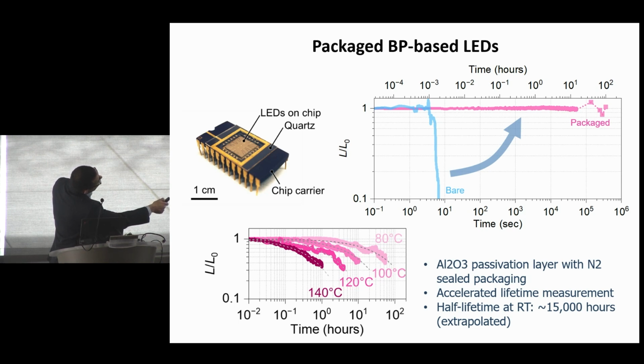Here, it looks like it's noise, but our photodetector ran out of liquid nitrogen. You're talking about tens of hours, so we had to constantly fill the liquid nitrogen in the detector. So the devices are very stable. We did the half-lifetime measurements by doing accelerated lifetime studies. That's what is being shown here. We operated devices at different temperatures, up to 140. We extracted activation energy. So the half-lifetime that we got at room temperature is 15,000 hours of continuous operation for these devices. So for the case of black phosphorus LEDs, they're actually very stable.